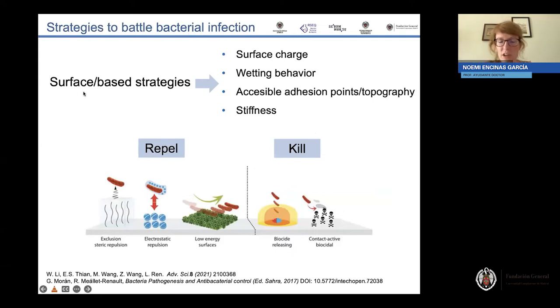Traditionally, surface-based strategies are found, both on designing surfaces that can repel this adhesion of bacteria or kill the biofilm whenever they are already formed. As I have stated beforehand, this second type of approach, the killing ones, are a little bit more complicated and, due to the toxicity effects and antimicrobial resistance, in my case, I try to avoid this type of approach. Based on the repel strategies, what we can do is to modify the surface charge, the wetting behavior, the adhesion points that are accessible to microorganisms, so thus the topography of the surfaces, and also the stiffness, which is going to affect the ability of live material to adhere on a surface.